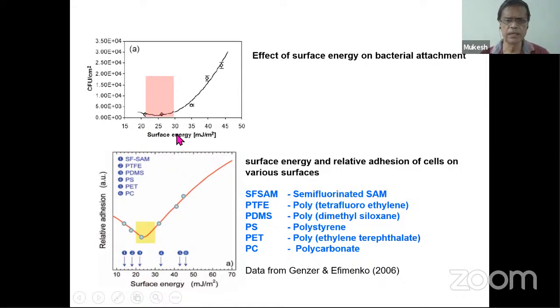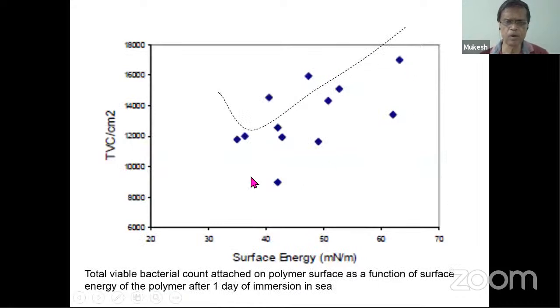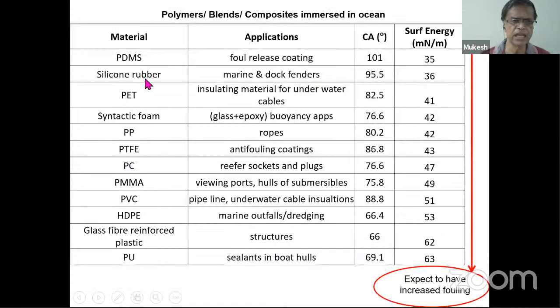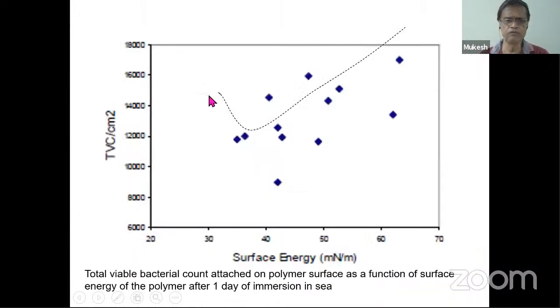And this is what we have seen in our study also. We have used a large number of polymeric materials, like PDMS, silicone rubber, syntactic foam, polypropylene, polytetrafluoroethylene, polycarbonate, polymethyl methacrylate, polyvinyl chloride, high density polyethylene, glass fiber reinforced polyurethane. All these are used in the shipping industry in various parts of ships, ocean going vessels, boats, underwater buoys and submarines. In this beautiful graph you can see that as the surface energy increases, the biofouling is high. As the surface energy is very, very low, the biofouling is also high. So there is an optimum number, and if we can work with materials which have this surface energy, we can really achieve a low biofouled material, which is well accepted by the shipping industry.